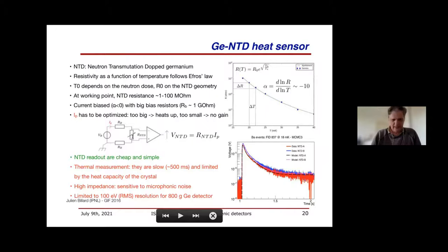One of the very good thermistors that you can use at 10 mK or down to 5 mK is called germanium NTD, a neutron transmutation doped germanium. You take a small germanium crystal and expose it to a strong neutron flux that creates a lot of defects, and you stop at the moment of the transition from being a semiconductor with the typical 50 ohm resistance to something very resistive because it's completely amorphous. It depends strongly on temperature. It follows the Efros law, which is an exponential of a square root of some reference temperature divided by the temperature of the electrons flowing through your NTD. And it's a logarithmic curve, and therefore that provides quite sensitive